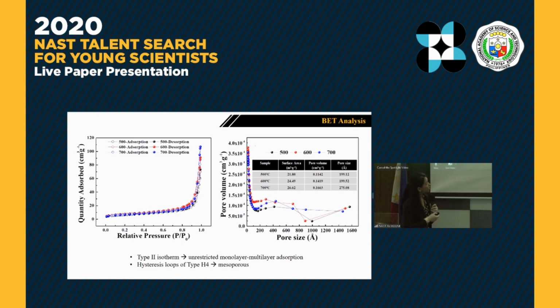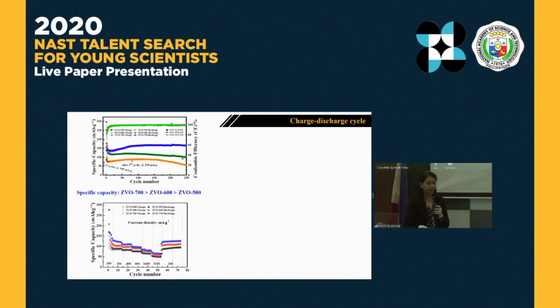In addition, in this experiment, we considered three calcination temperatures, that is 500, 600, and 700 degrees Celsius. As you can see, based on the BET analysis, as the calcination temperature increases, the surface area as well as the pore size also increases. These three samples were examined as anode material for sodium-ion battery.